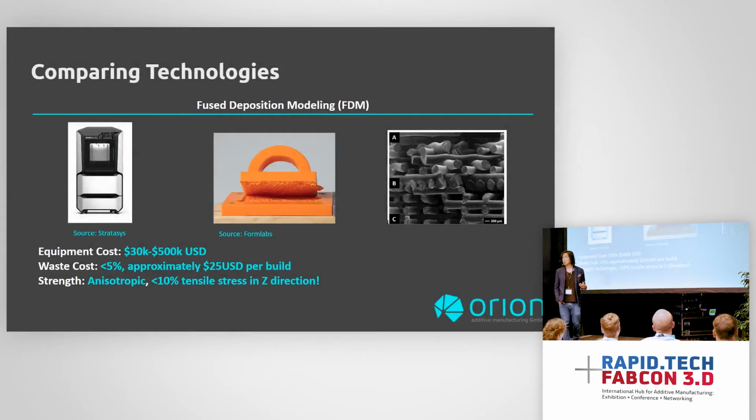The other option for printing with aerospace-grade materials is FDM printing. I know, FDM is like so 2010, right? But just hear me out for a sec. It's a single machine, single process, and it's much cheaper. Not only that, but you're also limiting the amount of waste. The only waste is in the support material. But it comes with one big caveat, which is the anisotropic strength. Anisotropic strength is when the strength in the Z direction isn't the same as in X and Y. This happens particularly with materials like PEEK, where you'll see the strength in the Z direction as low as 10%. That's really low.